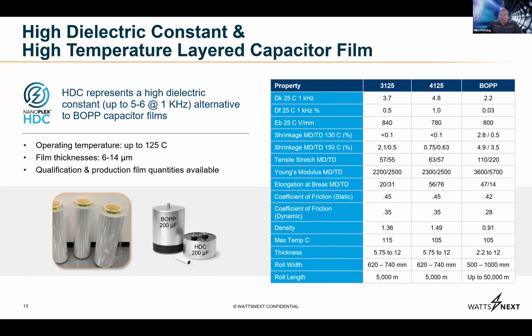But for certain applications, especially some pulse power applications, HDC is where it really shines. What you can get by going to the nanoplex material that we make is illustrated to the left of the table there in the capacitor pictures. These are wound metallized dry capacitors. We made 200 microfarad capacitors out of the same film thickness. The one on the left, the BOPP, is about twice the volume, twice the height of an HDC capacitor, which holds the exact same amount of energy. So if you're building capacitors for an application that requires hundreds or thousands of units, you want to take up the smallest amount of real estate as possible. HDC provides you with a solution you've never had before.